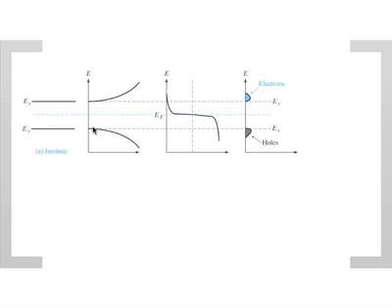Same thing happens for holes. Of course, the available states for holes is huge as you go lower or increase the hole energy. But the probability that they are unoccupied is pretty much 0, so they're really not there. So both these things matter, the available states and the probability that those states are occupied. As a result, we get a distribution which looks like this. This is our goal, the concentration of charge carriers. We want to calculate this quantitatively.